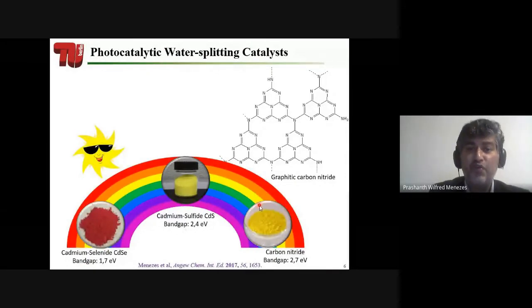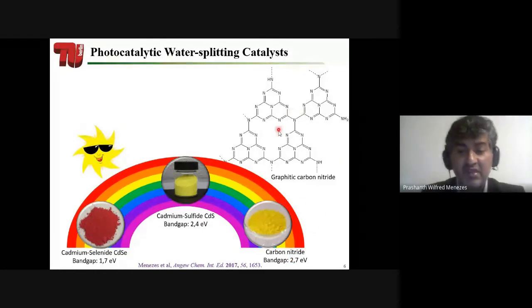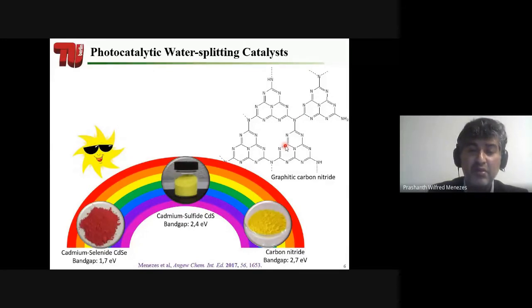Just to show you some of the photocatalysts we have worked on in the last few years, this is cadmium selenide, which has a band gap of 1.7 electron volt. And then we have cadmium sulfide with a 2.4 band gap. And recently we were working on carbon nitride, which is an organic semiconductor and has a band gap of 2.7 electron volt. This is the structure of this carbon nitride. These are very promising catalysts for hydrogen evolution reaction.